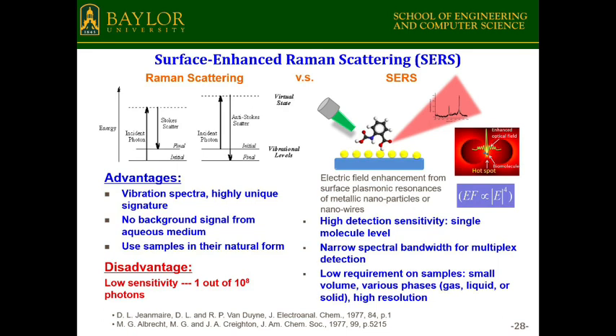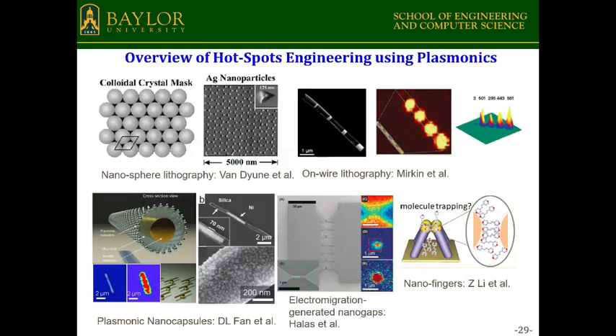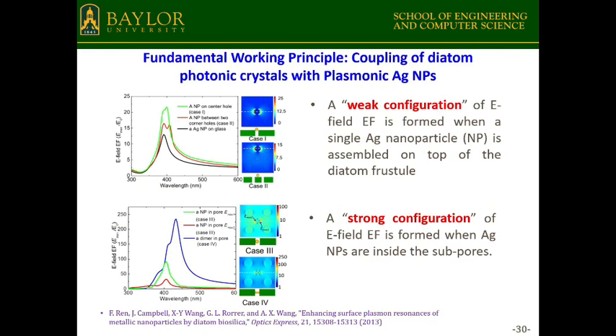And with that enhanced electric field, you can greatly increase the sensitivity of the Raman. We call this surface enhanced Raman scattering, or SERS. And you can actually detect a single molecule with a good engineered SERS substrate. And indeed, in the last 20 or 30 years, a lot of metallic nanostructures have been developed to enhance the SERS sensitivity. But my group takes a slightly different approach.